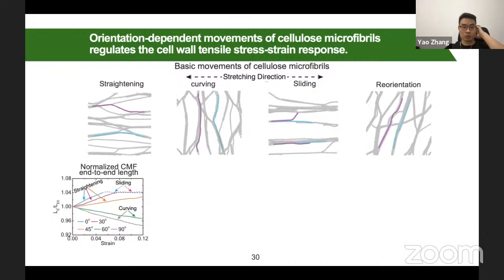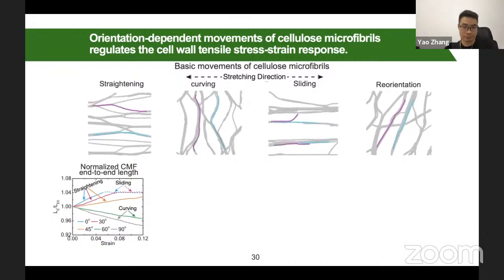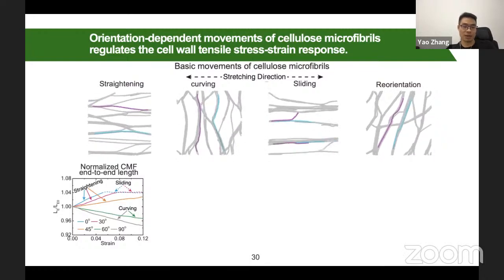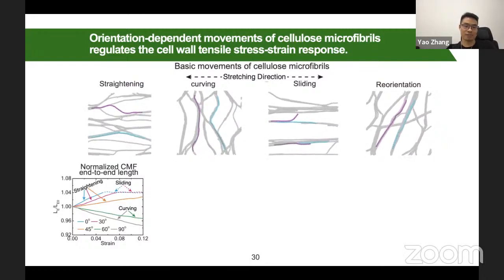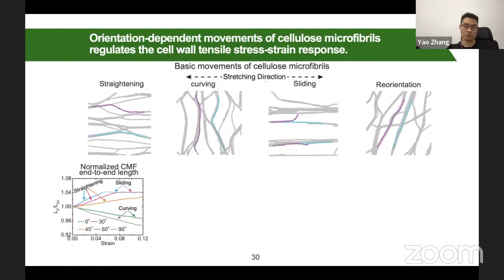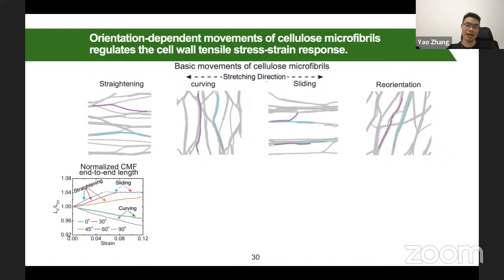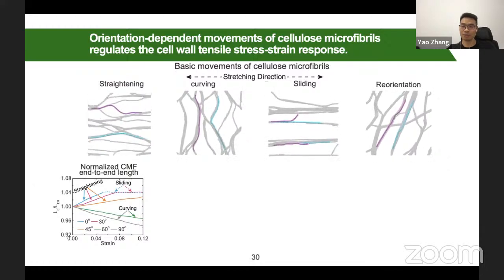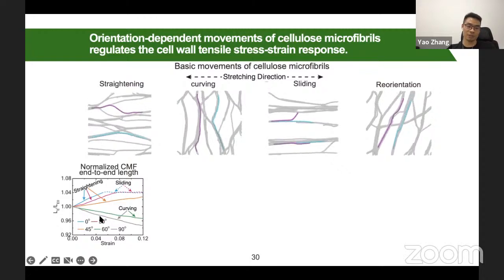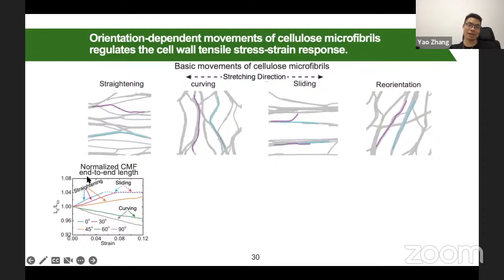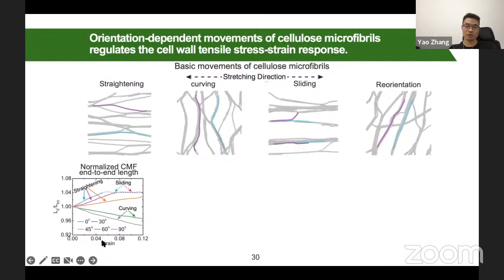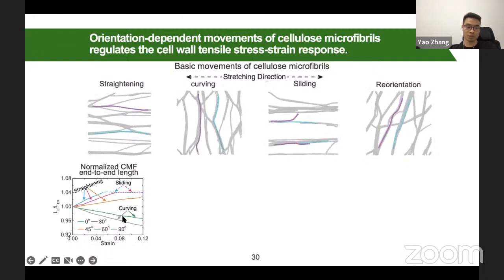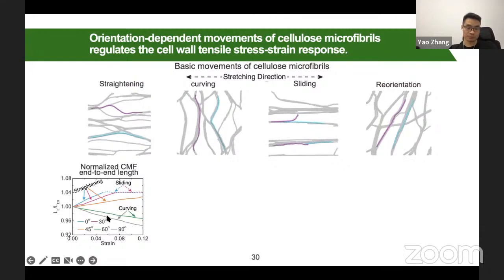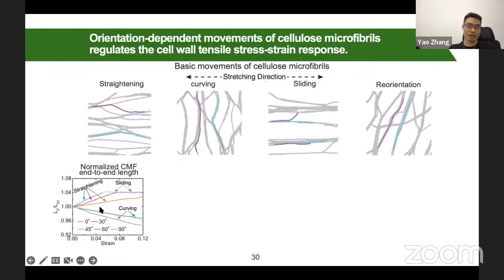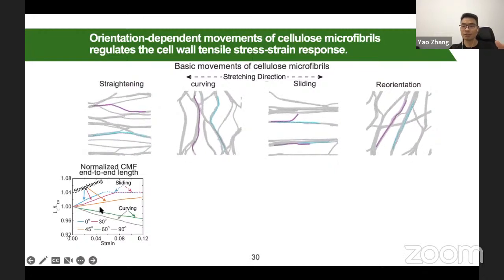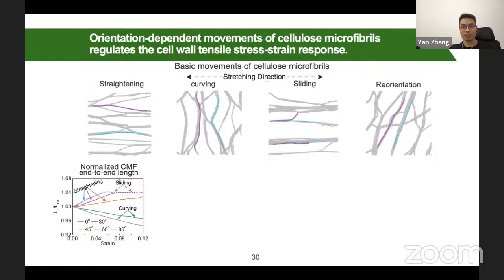And we check this: how does this fiber move during the stretching process? So first, check the end-to-end length of the fiber. If you look at this figure, it shows the normalized end-to-end length as a function of strain. In this case, we just stretch a single layer of this cellulose.